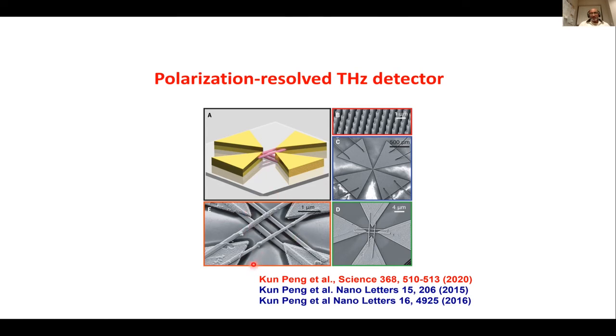You can see the close-up of this electron microscope image of these nanowires, and then these metal bow tie antennas, and then the nanowires at the bottom. The key challenge has been that the top nanowire should not be in physical contact with the bottom nanowires. So that's been a challenge. So that's where Kun Peng has spent a lot of time optimizing these things.